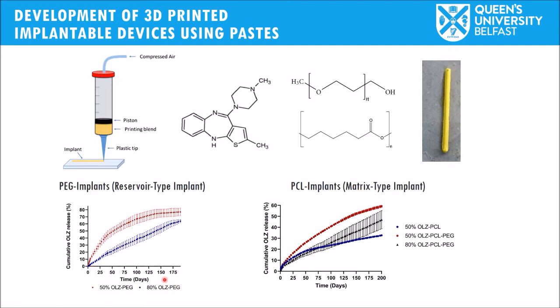Higher drug loadings will translate into a more concentrated or saturated environment inside the membrane, inside the pouch of the polymeric implant, and it will end in a zero order release, while with lower drug loadings, as you know, the supersaturation or the saturation inside the implant will not be maintained through all the process. We'll have a different type of release profile.